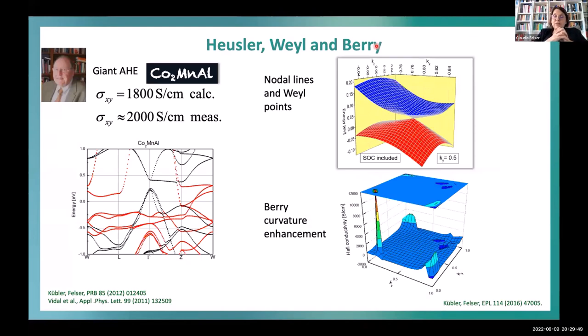And people believed for a long time, because the Hall measurement curves look exactly like the magnetization curves, that this only scales with the magnetization, but this is not true. Already in the Heusler, we found, before semimetals came into the interest of general research, that there are Heusler compounds which have giant anomalous Hall values. So there was even a patent here in Mainz based on this. At this time, we already recognized that this giant value always appears if you have crossing points in the electronic structure of this material.